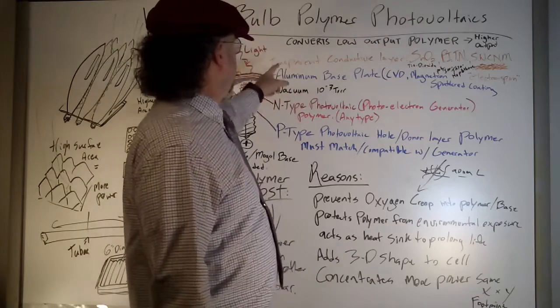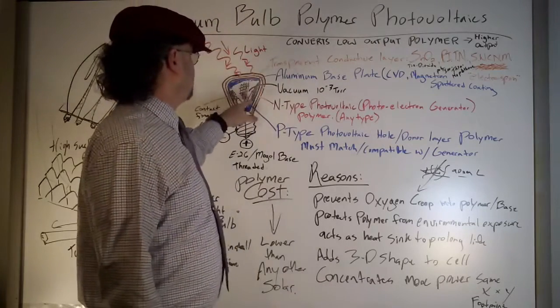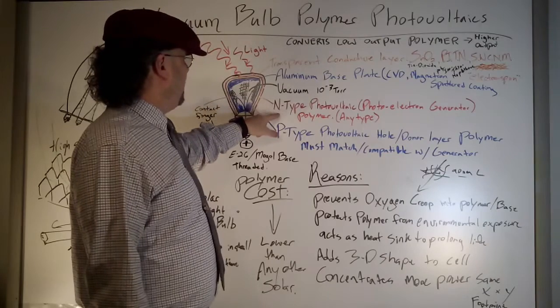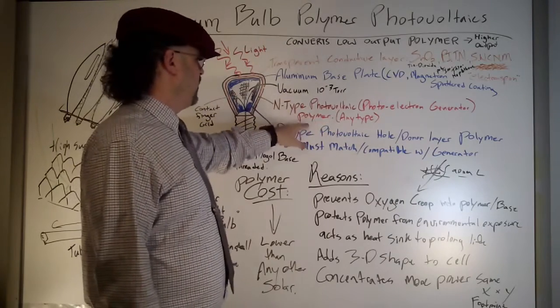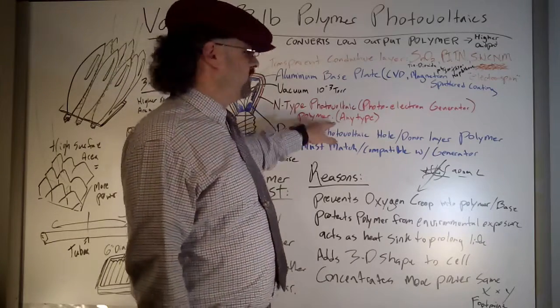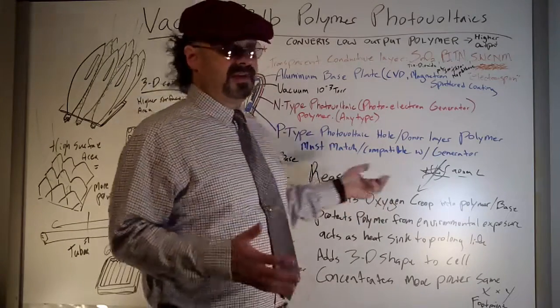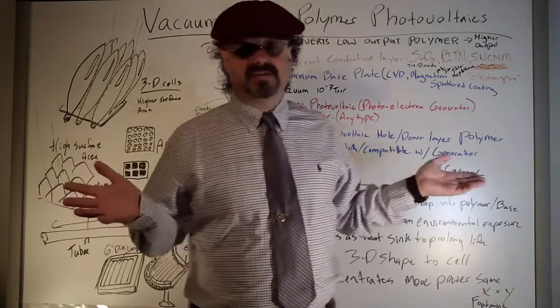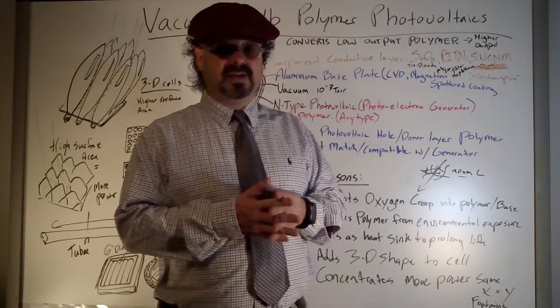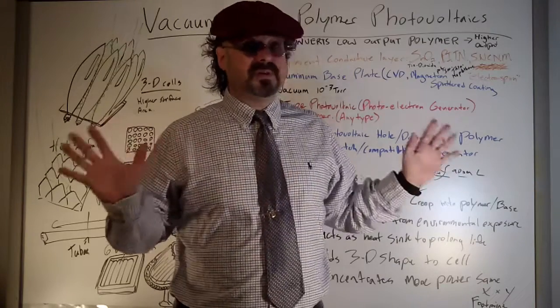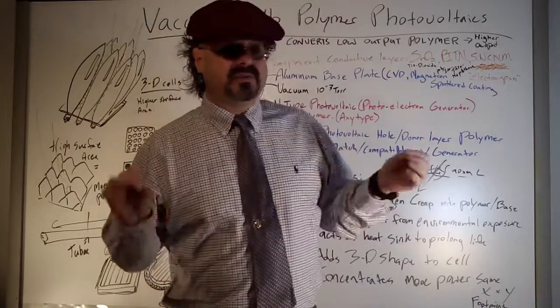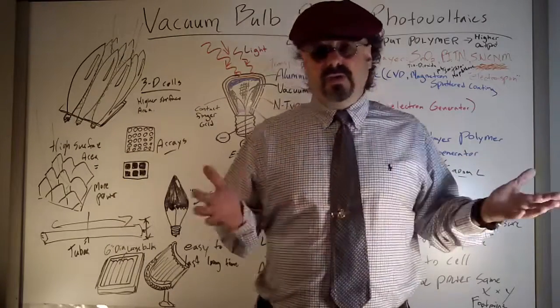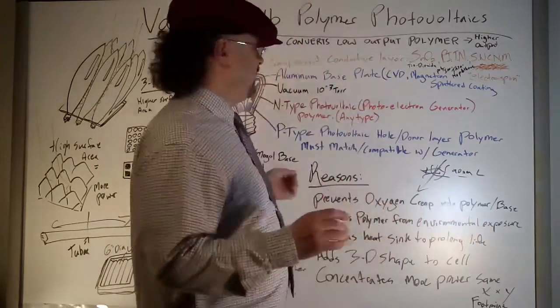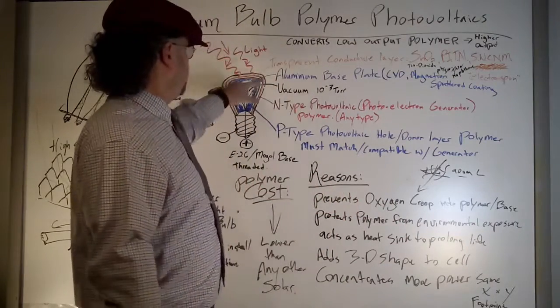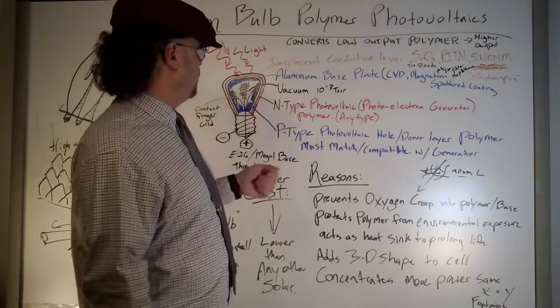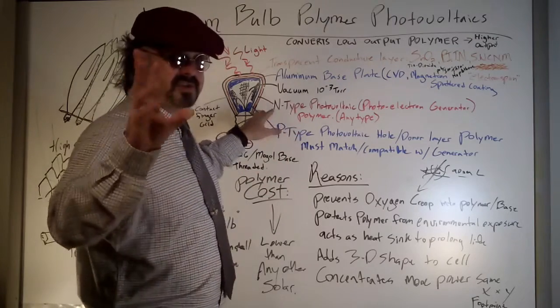Okay, so your transparent layer is on the inside of the glass bulb. The next layer you're going to have is an N-type photovoltaic photoelectron generator polymer. There's a bunch of different ones out there. Some of them use dyes, some of them use actual elements. Cadmium telluride is one of those, and there's cadmium sulfide. Once again, we're dealing with cadmium, relatively rare or more rare materials, but you could probably also use a phosphorus embedded in an epoxy or something like that. So there's another way we could do this, but let's just deal with generalized.